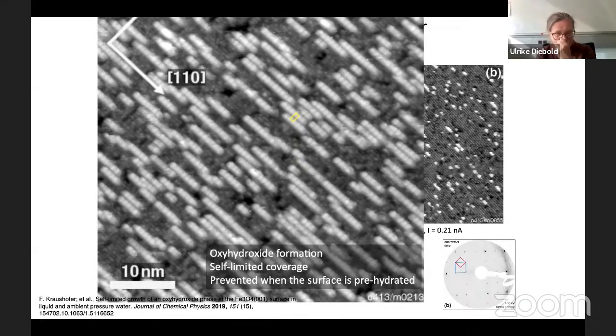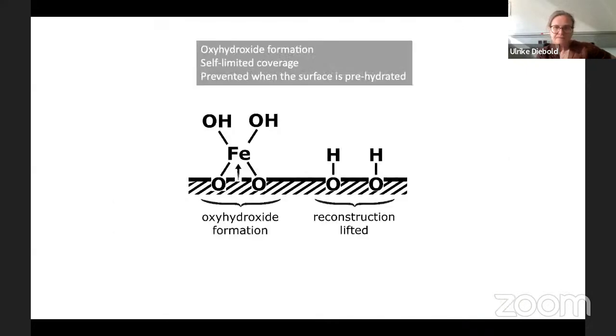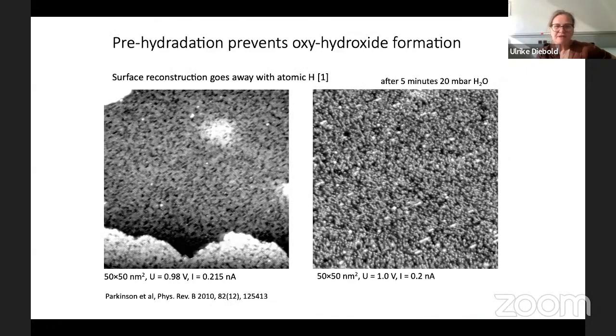An interesting side note, we played around a little bit. It turns out that when we have the surface, we can first put atomic hydrogen on the surface. We can do really strange things. We can first put atomic hydrogen on the surface and then expose it to, this is essentially also a liquid water film, 20 millibar. Then the surface will not change. It will stay exactly the same. So a hydrated surface will survive in liquid water. So yeah, that's where we are.